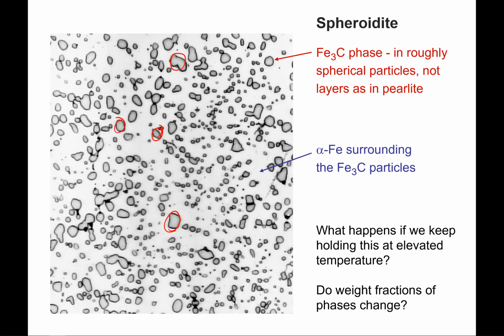Now this looks a lot like the tempered martensite that we just looked at, except that the length scales differ. I don't have a bar on this one, sorry, but if you take a look in your textbook when you're reading, take a look at the magnifications, and you'll see that this spheroidite is on a much bigger scale than the tempered martensite. And so here the separations between the dislocations are much larger, and so this does behave as a very soft, weaker material, but with very high ductility. Again, these particles here are the cementite, and this is the matrix of ferrite.